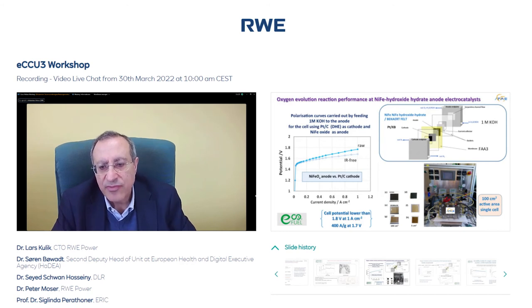This means that the anode oxygen evolution process is not the rate determining step in this overall process of co-electrolysis of carbon dioxide and water, as we will see later. And we have achieved mass activity exceeding 400 amperes per gram at 1.7 volts using this improved anode electrocatalyst. And these results have been achieved in a practical single cell of 100 square centimeter.